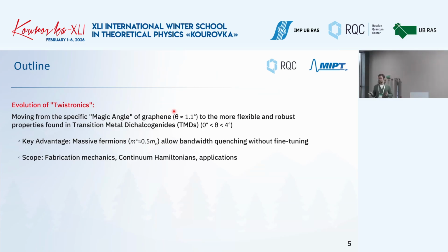Maybe for you it makes not much difference, but in the experimental realization, it is rather important, because for graphene, if you want to find this magic angle and these unique properties, you really need to struggle hard to make 1.1 degrees, and then when you set them at 1.1 degrees, it might twist a bit, and as a result you will not get the physics that you're expecting, and then you need to make like 20 samples to demonstrate it is working. So the key advantage of using another type of materials is that they have massive fermions, and they allow this bandwidth quenching without fine-tuning, and we will discuss this.